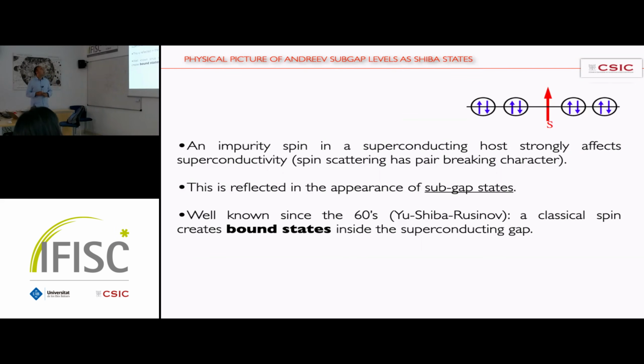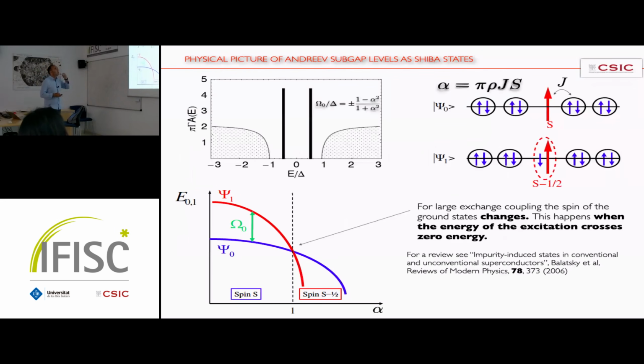And this breaking of Cooper pairs is reflected in the appearance of subgap states, states that live below the gap of the superconductor. You can bind states in the superconductor by breaking Cooper pairs. So this is the cartoon. You have a spin here, which is exchange coupled to the electrons forming the Cooper pairs. This is parameterized by alpha. This is J times S, the spin.